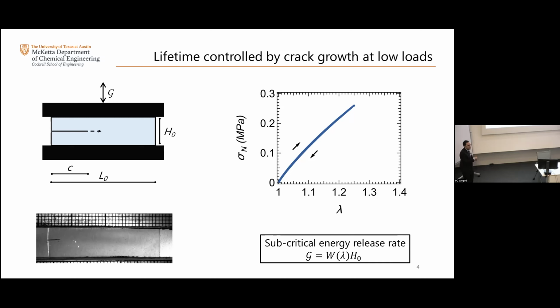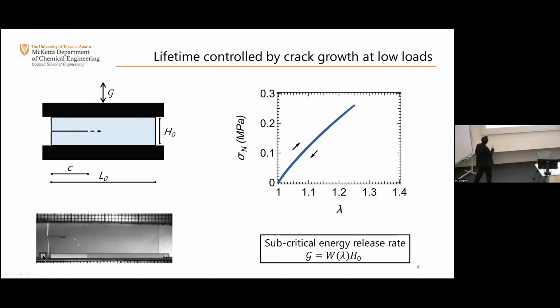Instead of taking the system all the way to the fracture point, what you do is cycle it for many, many cycles at very low deformations. So here is a video where each frame that you see corresponds to about 5,000 cycles. And you see, your crack is going to grow slowly, okay?